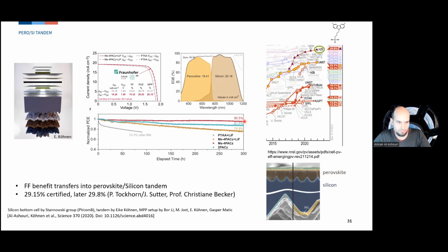So 95% after 300 hours in air was still retained. And so what's to take home is the fill factor benefit from the single junctions also transferred into the tandems. So that's how we know. I mean, it's one of the limiting factors, right? Hole extraction efficiency.